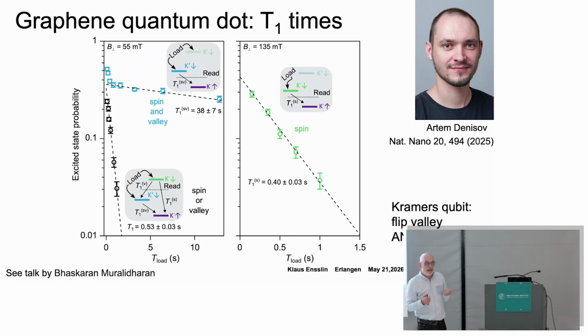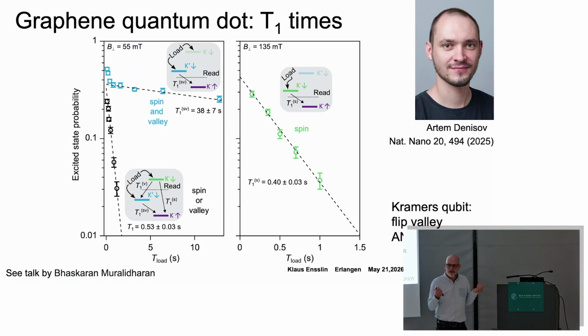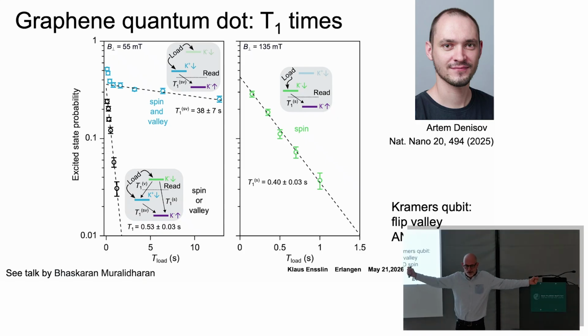Now think of the valley qubit. What is the valley qubit? Well, the valley qubit is you're at K or K prime in K space. You are at the same position in real space, you have the same spin, you don't couple to electric and magnetic fields. So you have to go a huge distance in K space. It's the size of the Brillouin zone. How do you get from K to K prime? Well, you need a very short-range scattering event. You need an atomic defect. If you don't have an atomic defect in your system, you don't make it from K to K prime.